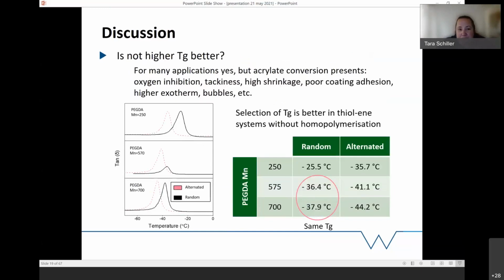So, a postulation of a question there. Is a higher Tg better? In the case of acrylates, basically no. You don't get as much control over the network, you start to get tackiness, you basically get less curing. So as a general rule, it's a better idea of having things lower.